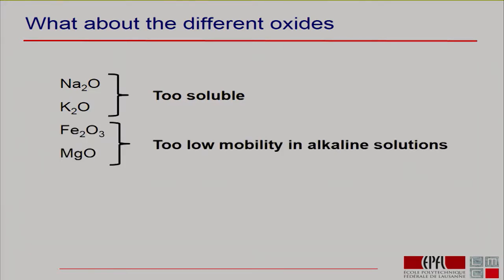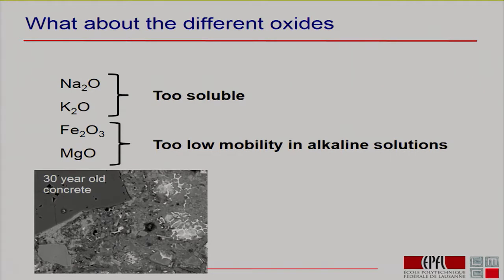If we look at iron and magnesium, on the other hand, we have the other problem that these have very low mobility in alkaline solutions. So, for example, here we see a micrograph taken from a piece of concrete that was in a building, 30 years old, and you see these bright white areas. Now, these bright white areas are where the iron is, and basically the reason they're so well defined is because they're in exactly the same place they were 30 years ago.